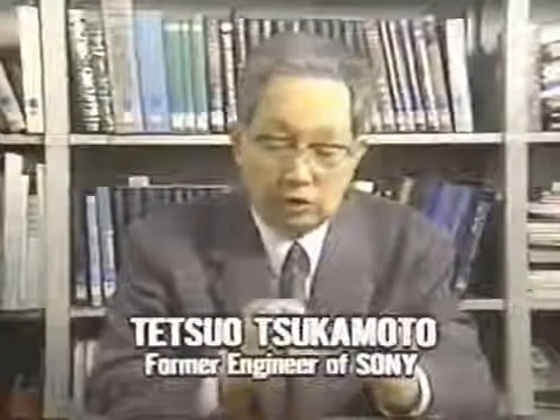Here's another look at how grown transistors are made. When gallium is entered during the seed crystal drawing, a thin P-type layer forms in the crystals. When antimony is added, N-type crystals form, creating a P-type layer in the middle. But there was a problem, the antimony. The drawback with antimony occurs during the drawing. It breaks apart and the P-type layer right in the middle disappears or becomes thin.